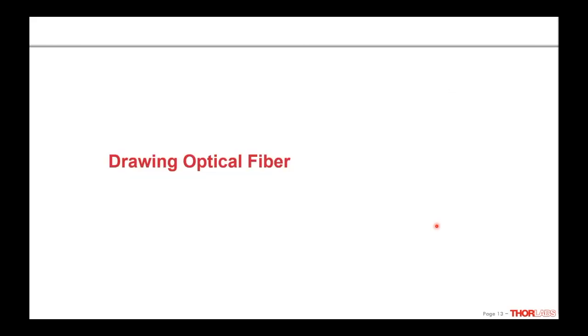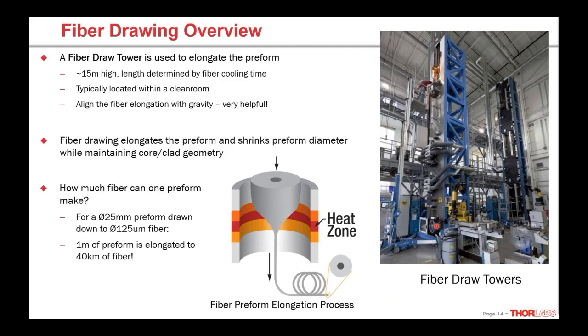To draw fiber we use very large equipment to make a very small product. The fiber draw tower is the apparatus used to elongate this preform into fiber. A draw tower is typically on the order of 15 meters high or higher — that height is dictated by the time it takes the glass to cool from top to bottom. The draw tower is typically located in a clean room, and the axis of elongation is aligned with gravity. We take this preform and stretch it, pulling it into a fibrous piece of glass while maintaining that same core-clad geometry — shrinking it in diameter while greatly increasing its length.